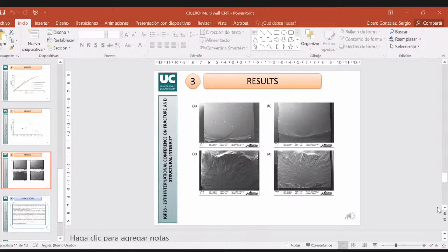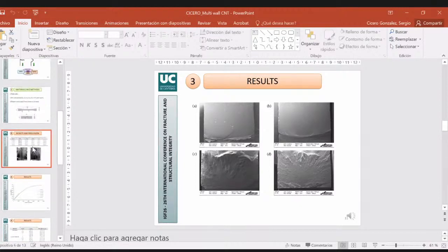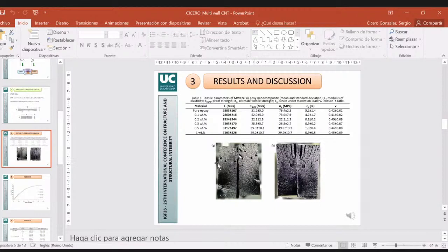So two problems here, basically. First of all, the difficulty to generate materials with higher amounts of carbon nanotubes. You may see how many pores were inside the material for higher amounts of carbon nanotubes. And the second problem is that even when you have a well-distributed material in the specimens, with 0.1% of carbon nanotubes, the effects on fracture behavior were negligible.